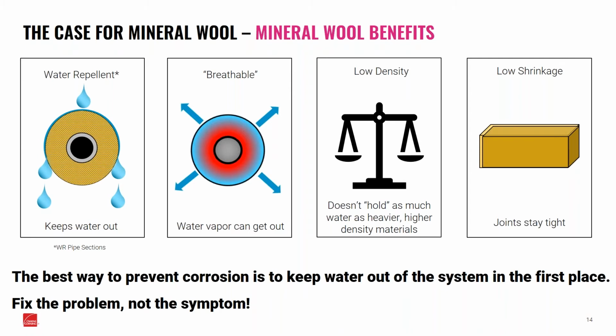It's also low density so it won't hold as much water. So imagine if your product holds 100% moisture content. Well, you'd rather have a lighter product than a heavier product. If you have an 8-pound product, maybe you have 8 pounds of water in it. If you have a 15-pound product and 100% moisture content, you're going to have 15 pounds in there. So the less water you have, the less you have to drive out or try and remove from that system.